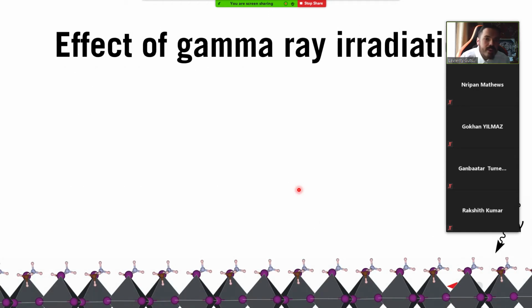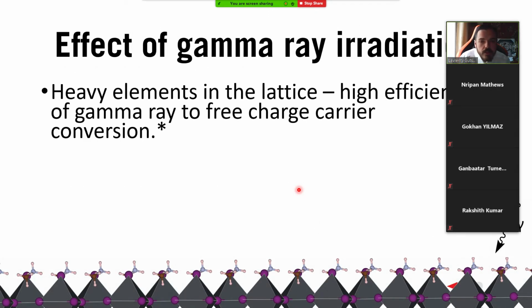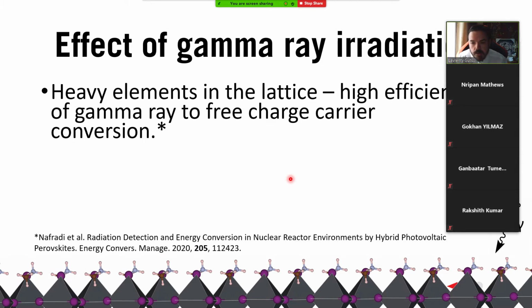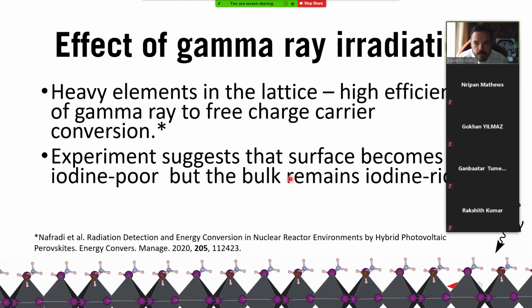So what do gamma rays do to the material? First of all, we have heavy elements in the material, right? Lead. So we have a high efficiency of gamma ray to free charge carrier conversion. This was studied very recently, in fact. Our experimental group showed that the surface becomes iodine poor, but the bulk remains iodine rich.